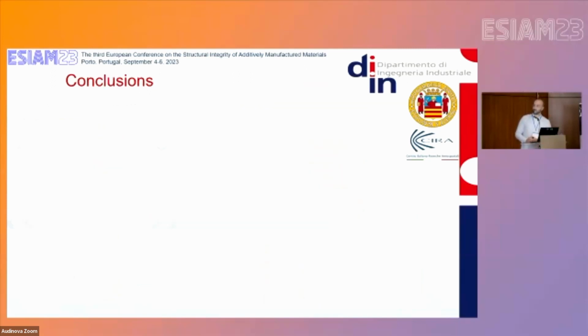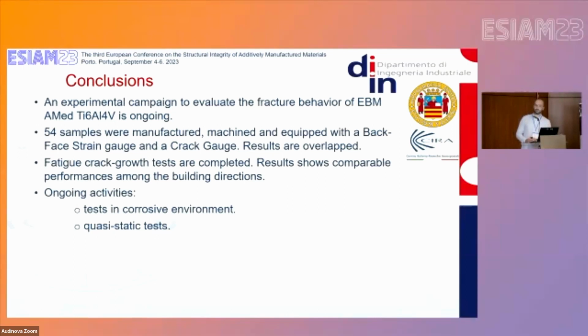And so to conclude, these are the conclusions. To sum up, I can say that we're developing this experimental campaign on this widely known material in corrosive environment and in air, in laboratory. And the interesting thing is that we are using a back-face strain measurement system that is very simply easier to use, because with one single strain gauge you can appreciate the variation of crack length during the whole propagation, from the smallest crack length to the largest crack length, with one single sensor.